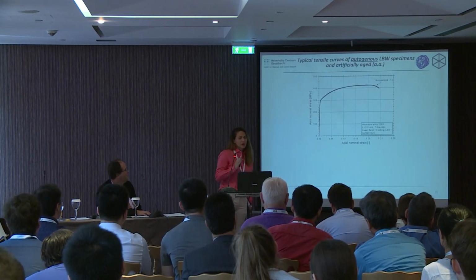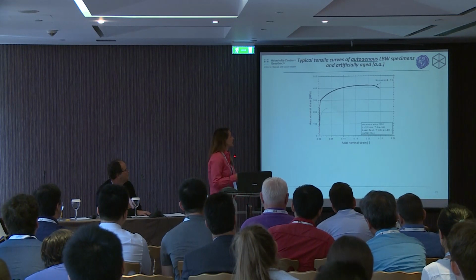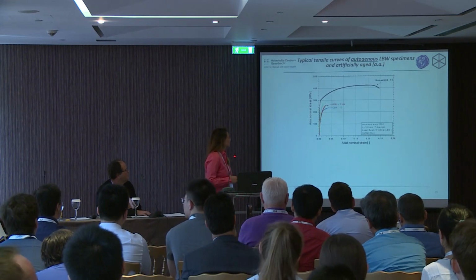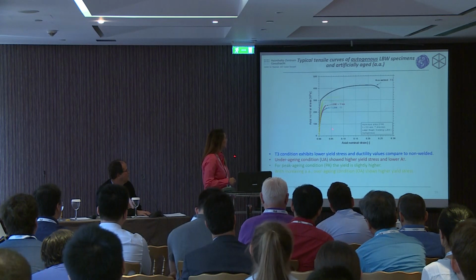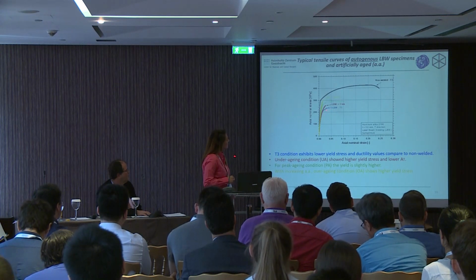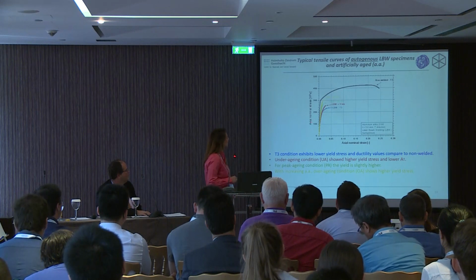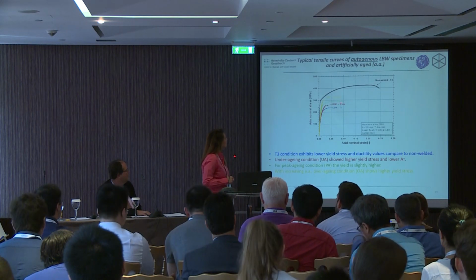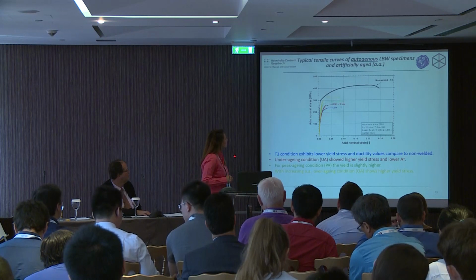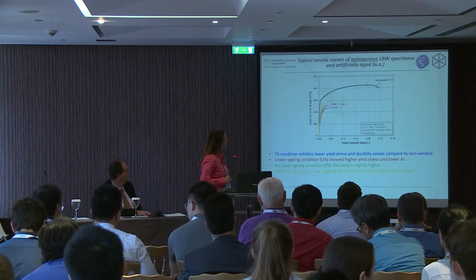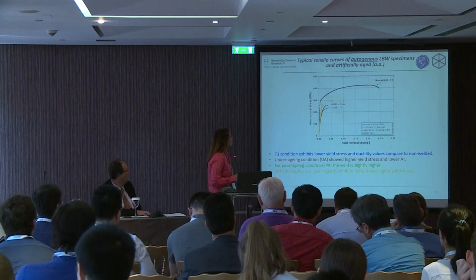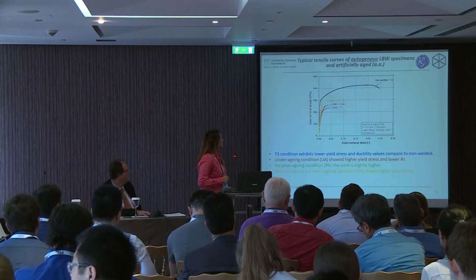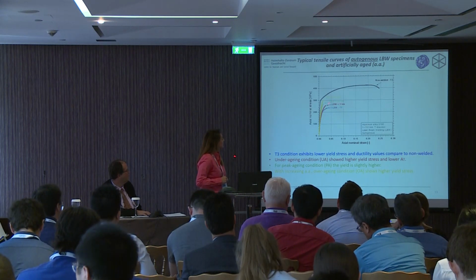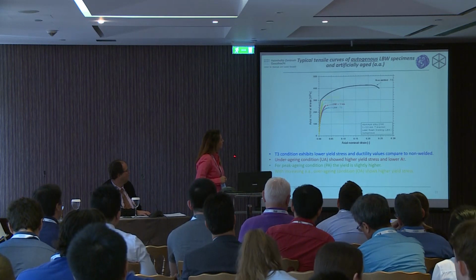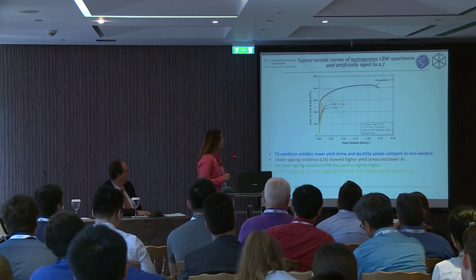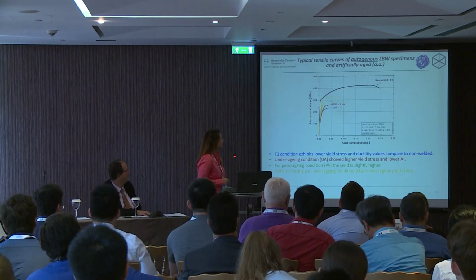The typical tensile curves for autogenous laser beam welding with increasing artificial aging time. You can see that T3 condition exhibits lower yield stress and ductility, of course, compared to non-weld. With increasing artificial aging, the under-aging condition shows higher yield stress and lower total elongation at fracture. At 48 hours, the yield stress is slightly higher, and for 98 hours, the over-aging condition shows higher yield stress.